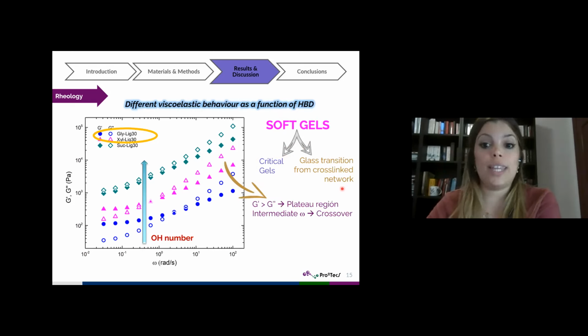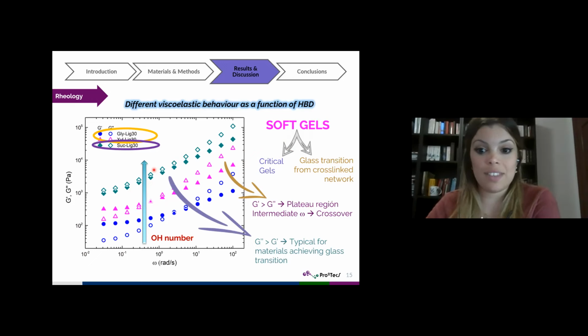In this way, formulations containing glycerol and xylitol as hydrogen bond donor compounds in the eutectic mixture show higher values of the storage modulus, the G prime, than the loss modulus at low frequencies, that tend to achieve a plateau region here. However, a crossover between both modulus functions was identified at intermediate frequencies, which is close to critical gel materials. However, for sucrose-based samples, despite the higher values of both moduli, G double prime was always higher than G prime in the whole experimental frequency range studied, which is the typical viscoelastic response for a material achieving a glass transition.